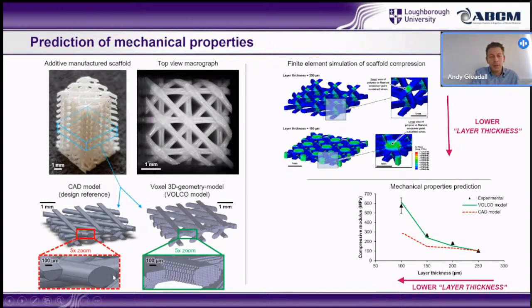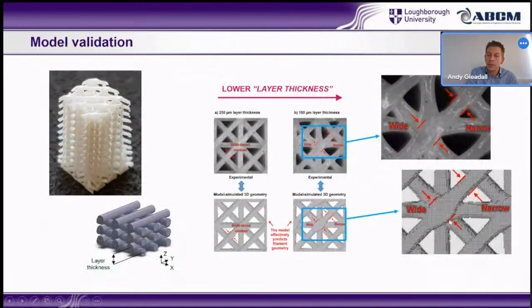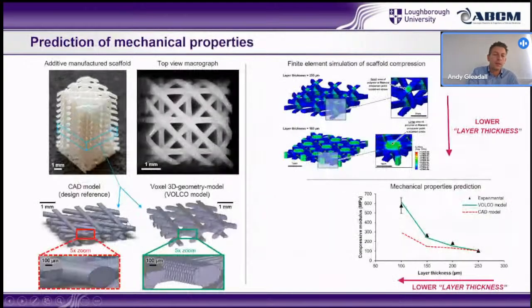And with that model, that exact geometry that you see on screen here compared to the Volco, when we did finite element analysis on that structure, that's what the red dotted line is in the plot to the bottom right. And you can see it just can't capture that trend because it's not capturing the fact that the filament is getting wider at crossover points. So this approach is not really representing what's going on in the printing process.